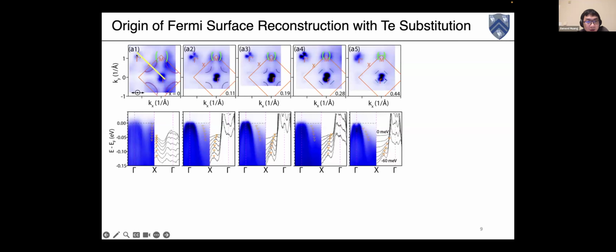So we take the cut along this gamma-X-gamma direction for these different dopings, and the second row is the corresponding gamma-X-gamma cut, and these triangular points are the fitted band dispersions, and they cross the Fermi level and form this dashed Fermi surface shown in the Fermi surface mapping. And so this shows that the Fermi pocket around this Brillouin zone X point actually comes from these very vertical-like bands at the X point, and these vertical bands gradually bend towards the gamma point and form these XY pockets we are familiar with.